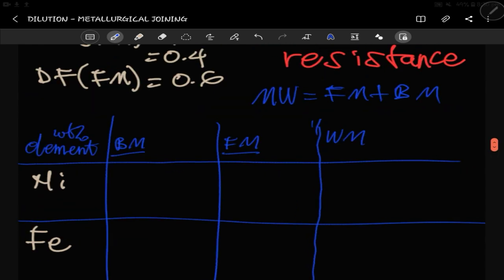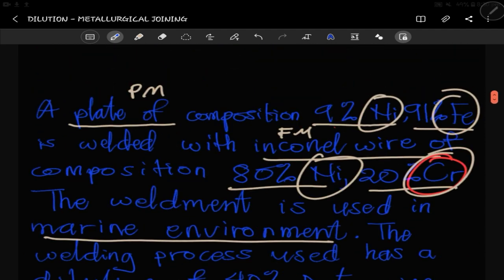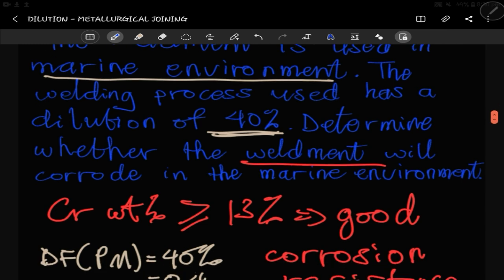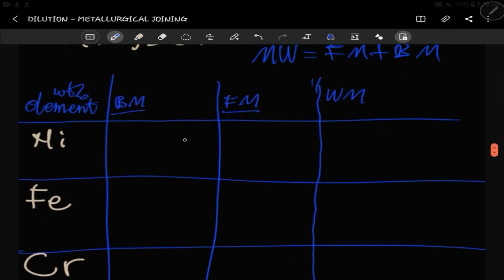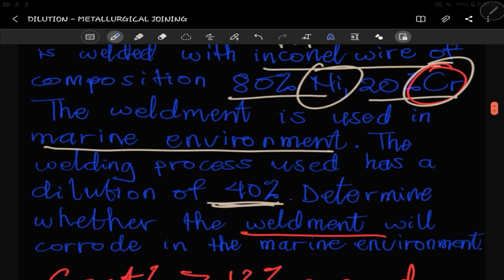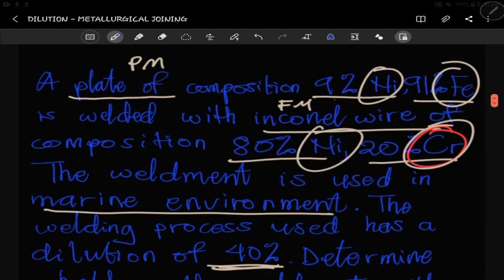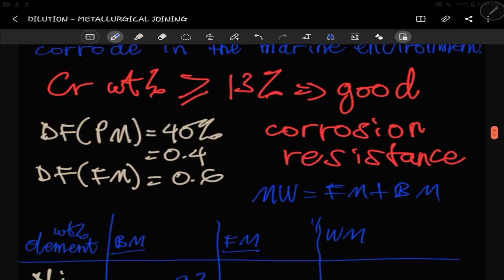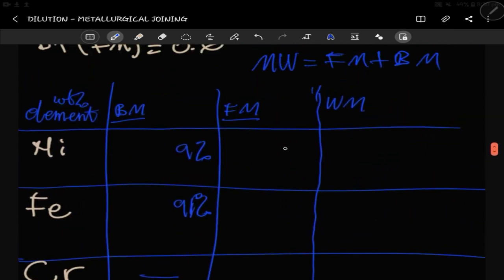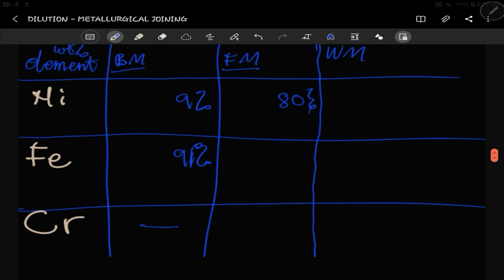Okay. So now we know that in the base metal, the parent metal, which is the plate in this case, nickel is 9%, iron is 91%, right? This will mean that there's no chromium in the parent metal. For the filler metal, we have nickel 80%, chromium 20%. This means that there's no iron in the filler metal. When you look at this, you should see clearly that the original percentages add up to 100, this plus this gives 100, this plus this gives 100. And so whatever we get at the end of the weld metal should be 100.